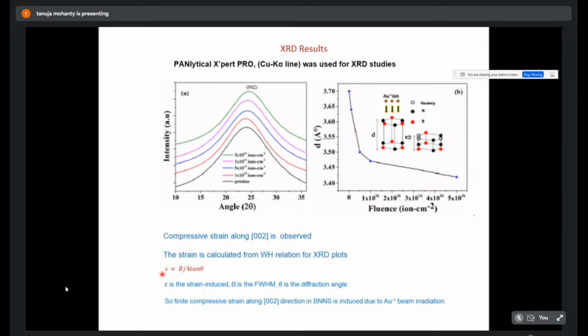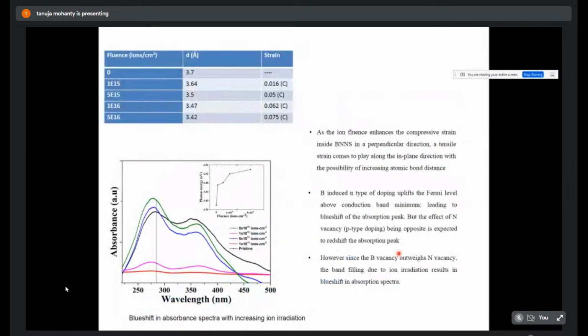From the Williamson-Hall calculation, that is, B cos theta equal to k lambda by D plus 4 epsilon sin theta, B equal to the FWHM, and theta is the angle. So strain is calculated, and we have also done this strain analysis. As the ion fluence enhances, the compressive strain in the perpendicular direction increases and a tensile strain comes into play in the in plane direction, and that creates a possibility of increasing atomic distance.